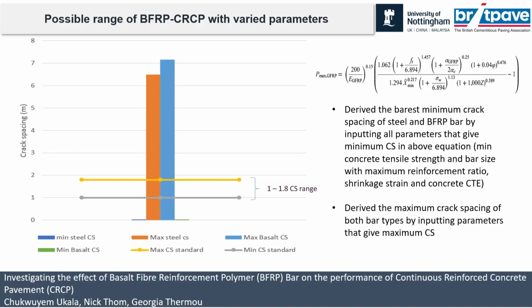Before I say that, finally, we looked at a range of all the possible minimum values that can be used. What we did is take the most minimum values that give us the crack spacing in all parameters, and then the highest values that give us the highest crack spacing, to see a range of what we can get. And we compared that with a standard of 1 to 1.8. I think the National Highways or the AASHTO recommends something like that. Then we decided to check that for steel, and we decided to check that for basalt.